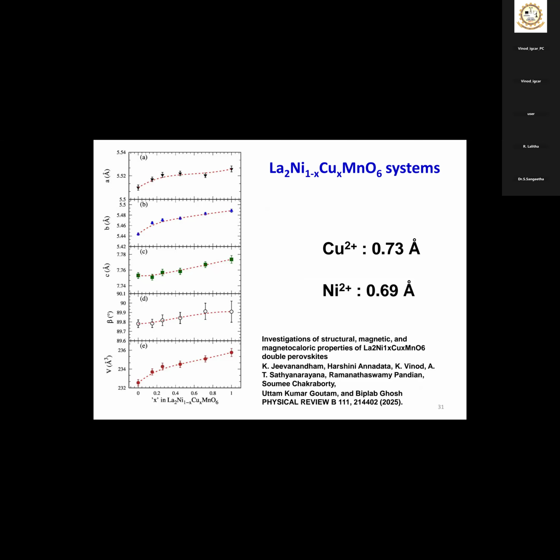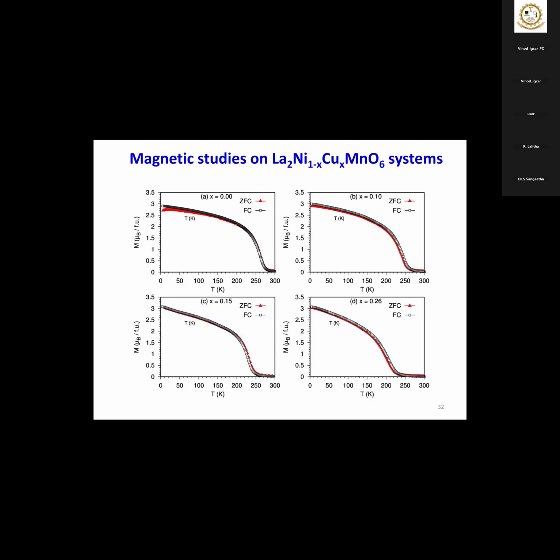You can see, as expected, lattice volume is increasing, because you are substituting with a slightly larger ion. And now the magnetization data. One more thing is nickel spin value is S equal to 1. Copper spin value is S equal to half. So the magnetic moment is also different. So this is the magnetization data.